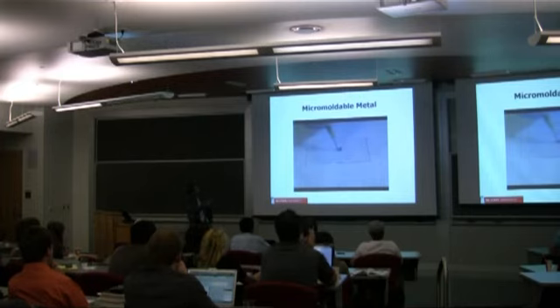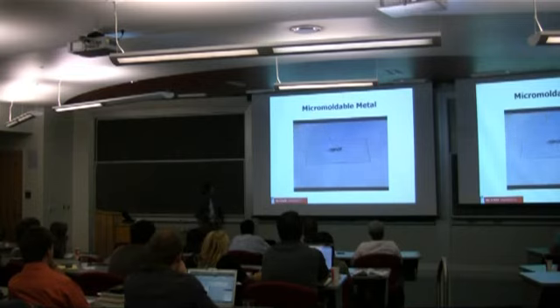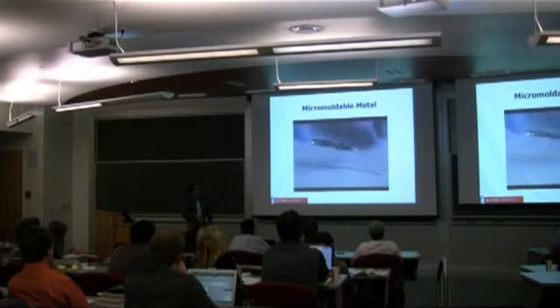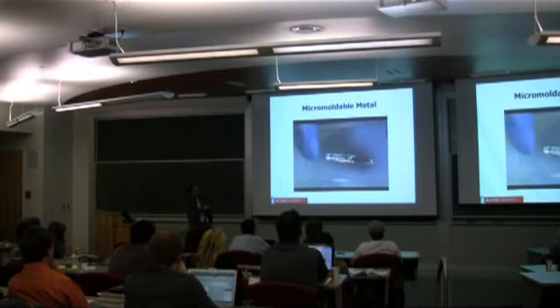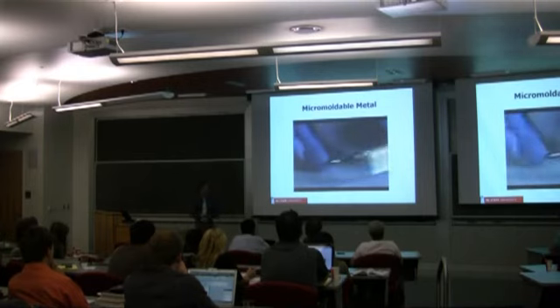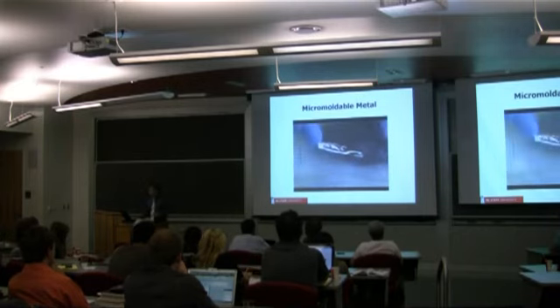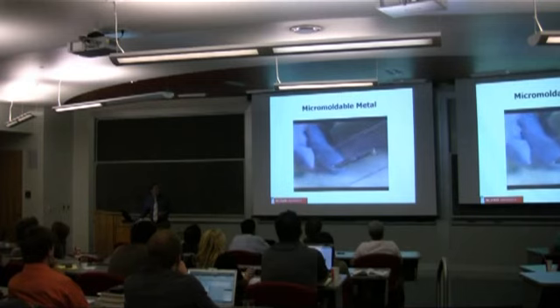This is a 2-inch by 3-inch glass slide, just a standard syringe. You can see that you can pump the metal out of the syringe, no problem. It's a low viscosity liquid, very much like water. But now you start to see something that's different than mercury. You can spread this out on the glass slide like wet paint. And then if you tilt the slide, you can see the metal flowing, sloshing back and forth, yet it maintains its macroscopic footprint. So it kind of holds its shape, it can still flow. And this is all at room temperature.